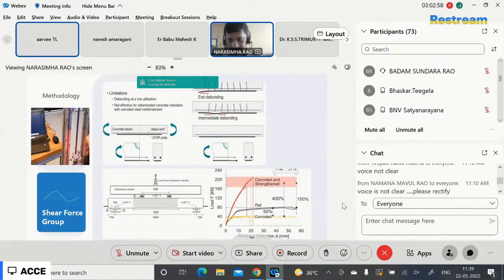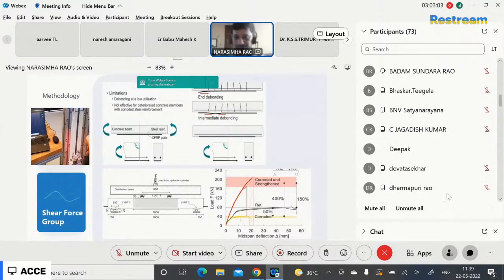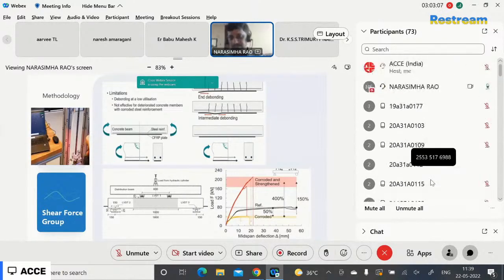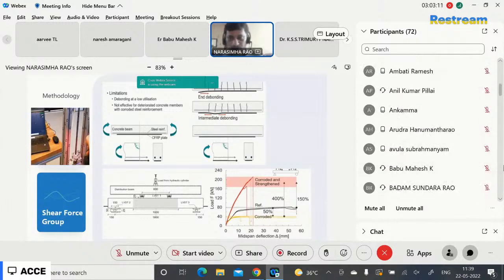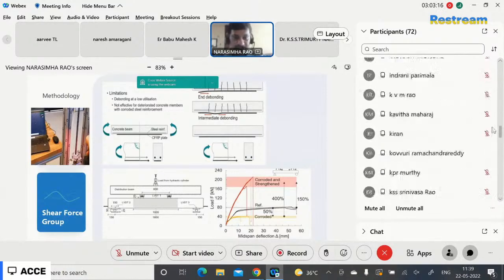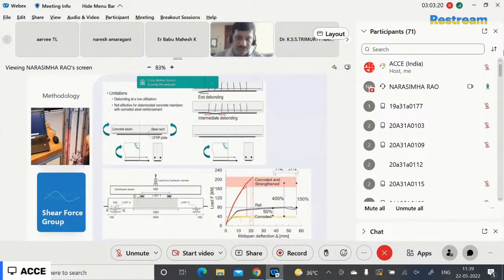Therefore, these load deflection curves give a qualitative assessment of the improvement from the FRP strengthening efficacy. And just as we have discussed, the debonding effect: debonding is the strain at which there is a separation between the laminate and the bottommost fiber of the beam, that is the corroded beam or the uncorroded beam, as the case may be. We are using the FRP laminate at the bottommost extreme fiber as an externally bonded material, and once the stiffness increases, there is an increase in the strain in the FRP laminate, and also an increase in the tensile strain in the extreme tension fiber of the beam. There is a strain at which debonding occurs, approximately 1.4 to 1.6%. That strain we call the characteristic debonding strain, which governs the strength of the laminate.